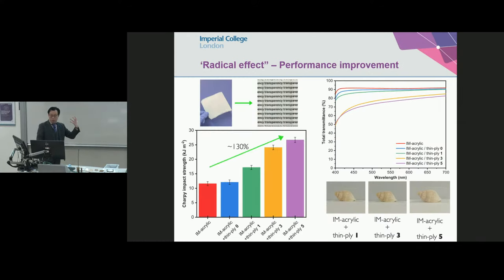So we then tested this thing in terms of performance. So these are the samples again sitting right in front of you. They are still transparent, as you can see from this graph up here, rather transparent, and the impact performance actually goes up as well. So that's all great. Having that, after 7 years of trying this thing, 7 years, we finally got there. You start off with this wet gel that you have here. You dry them out into a piece of paper, impregnate them with the right polymer resin, stack them up, it's transparent, and it does have improved impact performance. So 7 years, we got there finally at the end.